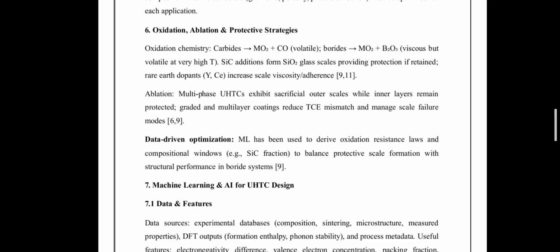The next is the oxidation, ablation, and protection. Oxidation behavior is often the ultimate performance limiter. Carbides oxidize to form carbon monoxide, which is volatile. Borides form boron oxide, which is viscous but volatile at very high temperature. Silicon carbide addition generally forms protective silicon oxide scales, while rare earth dopants increase the scale viscosity and adherence. Multi-phase and graded ultra-high temperature ceramics exfoliate the sacrificial outer layer while protecting the load-bearing core.